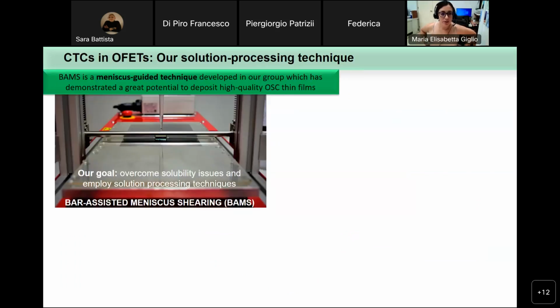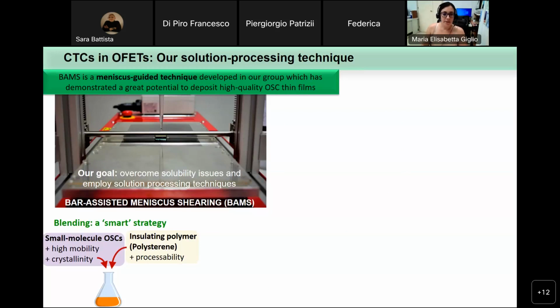In our group, basically we want to overcome the solubility issues about CTCs, and we want to employ a solution processing technique called Bar Assisted Meniscus Shearing. That is a technique that we developed in our group. The strategy when we use this technique is that we want to produce films from a solution.